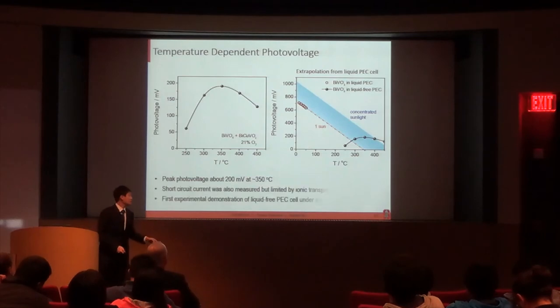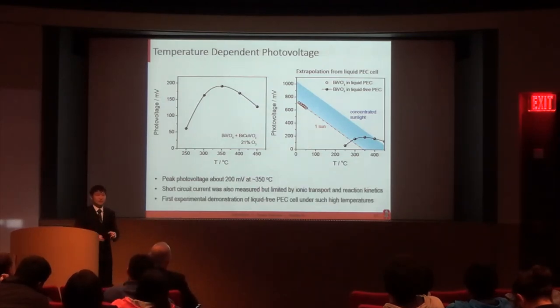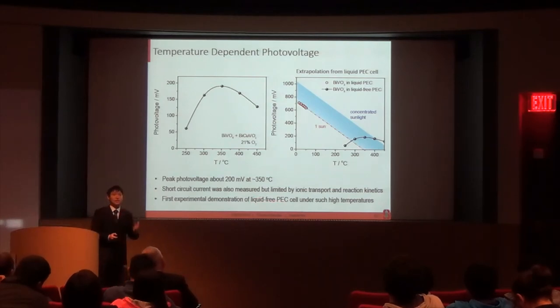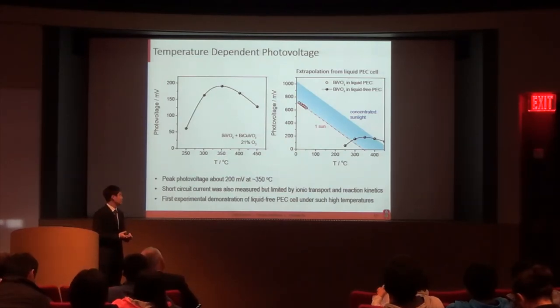And that tells us we have demonstrated experimentally for the first time a working liquid-free PEC cell under temperatures as high as 400 degrees Celsius. Although the photovoltage is still limited due to the intrinsic limitation in BVO, and photocurrent was measured but limited by ionic transport and reaction kinetics at this point. So there's still some optimization remaining to be done.